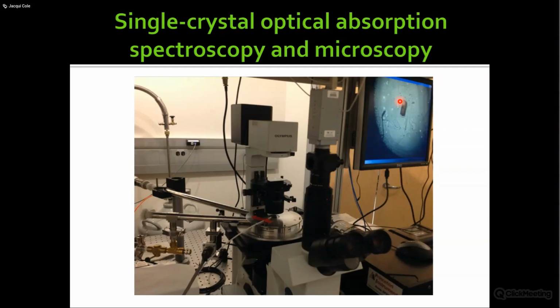So we can see what's happening with the crystal, and behind there's an optical bench, the breadboard there. Actually we use LEDs rather than lasers these days, and there's an LED light being passed through under there and up through the bottom of that microscope, so we can shine light on it. We have to be careful because there's also light coming down from the optical microscope. And there's also spectroscopy off the side on the left that we're running together with the optical microscopy. So it's concerted single crystal, low temperature, optical absorption spectroscopy and microscopy all in one go. And you'll see hopefully why that's important as we go along.